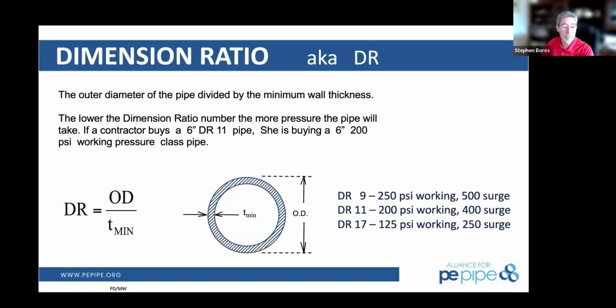Okay, yeah. So with polyethylene, you get a working pressure rating based on the maximum design stress of the material, but you also get surge allowance on top of that. With polyethylene, you get a recurring surge, which means it can happen up to 55 times a day for 100 years, and you can go 1.5 times above that maximum working pressure rating. For instance, you see the DR11 here has a 200 PSI working pressure rating. As long as you don't have surges above 400 PSI for occasional surges, you're fine. Up to 350 PSI, 300 PSI for recurring surges.